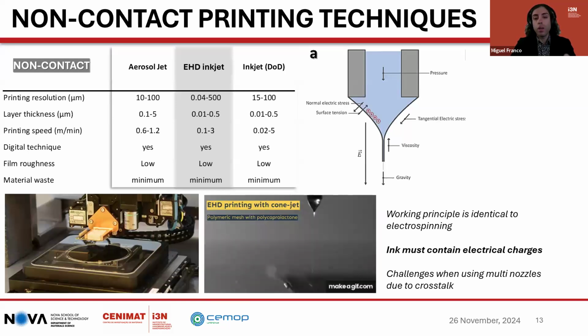Then there is electrohydrodynamic inkjet printing. It started as an advancement of inkjet printing in terms of printing resolution. It can achieve a printing resolution of up to 40 nanometers, and the working principle is identical to electrospinning, where it tends to draw ink rather than pushing it out, like in drop-on-demand inkjets. Since it relies on electric fields, the ink must contain electrical charges, and there are challenges when using multi-nozzles due to crosstalk, which can limit the scalability to industry.